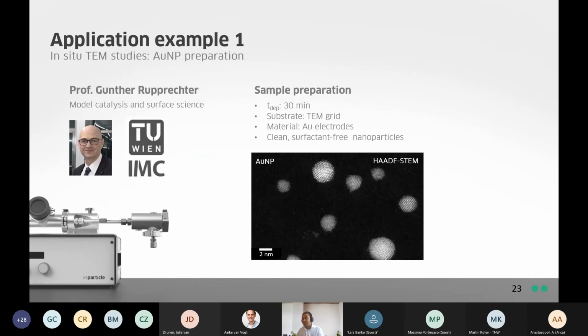There are a couple of application examples I'd like to share just to illustrate what we can do with these accessories. The first one is an in situ TEM study. This was done in collaboration with Professor Günther Rupprechter of the TU Vienna in Austria. He's interested in studying model catalysts. Here on the right, I show you a HAADF-STEM image of gold nanoparticles that were deposited on a TEM grid. It took 30 minutes to prepare this sample.